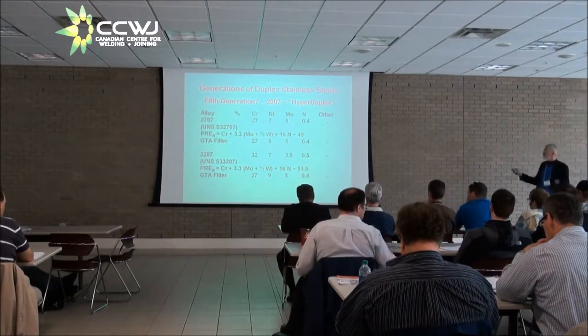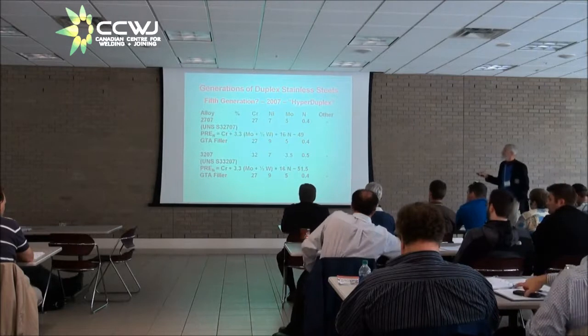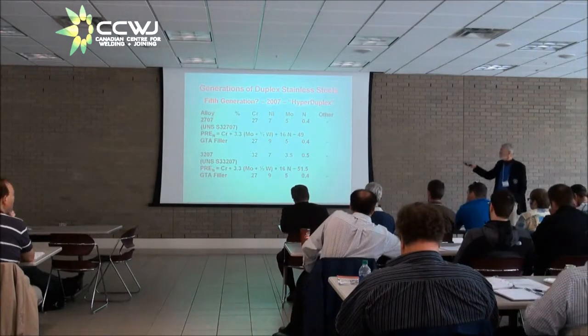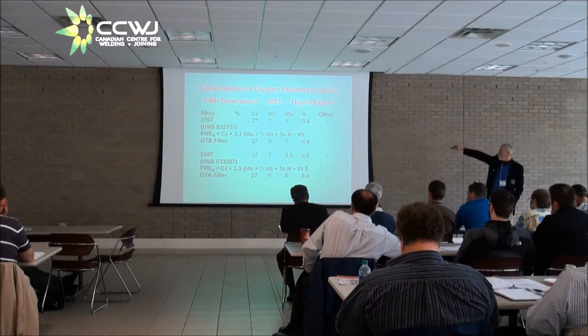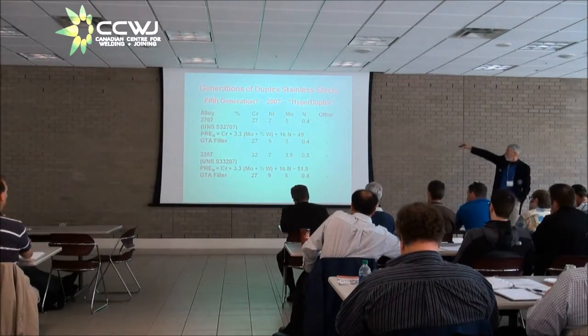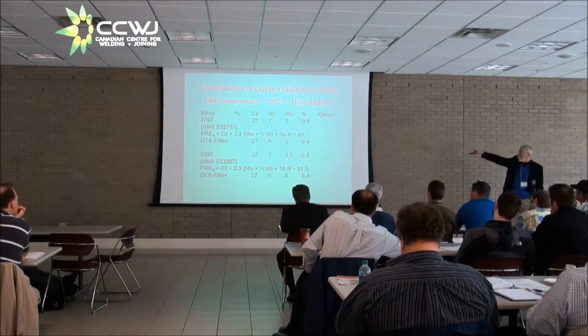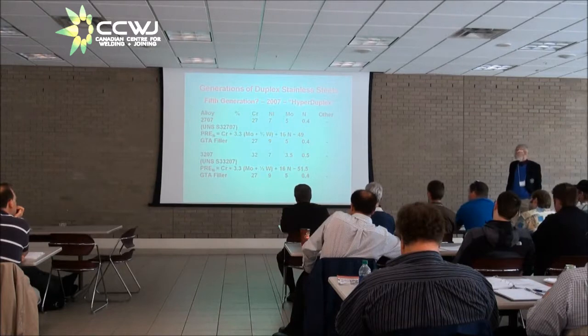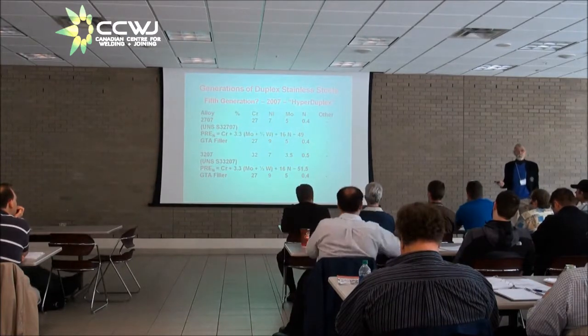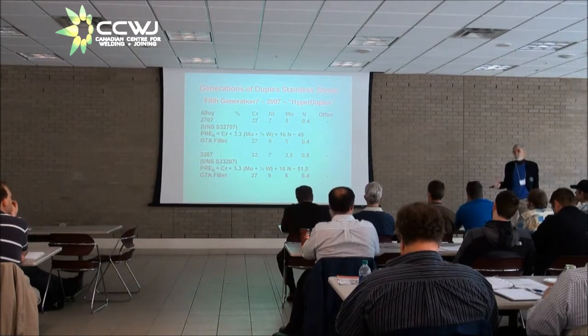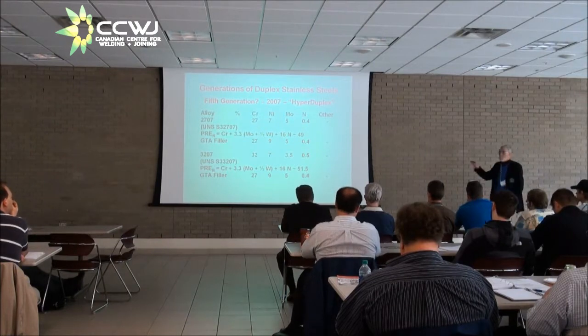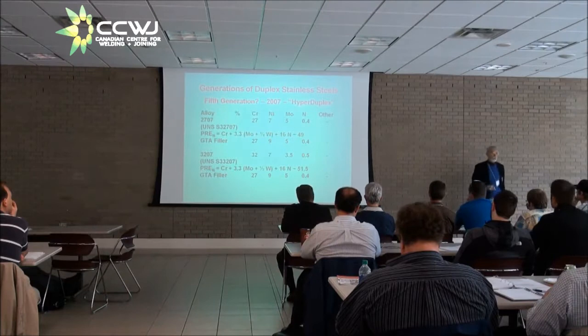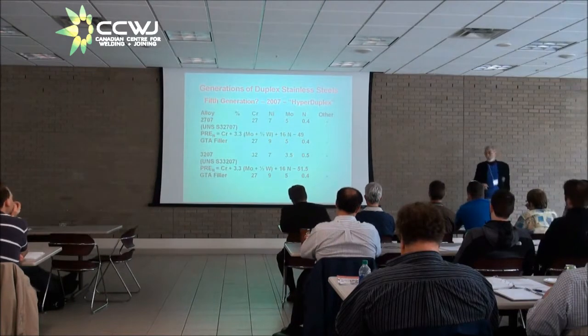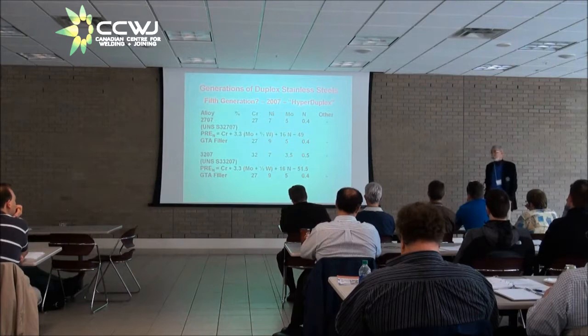The filler material that is proposed for these by Sandvik, who is the purveyor of the material, is 27 chrome, 9 nickel, 5 moly, 0.4 nitrogen, and it's the same filler material for both cases. That filler material is only available as gas tungsten arc filler material. That's the only welding method that's ever been used on those, as far as I know, to any extent. And at the moment, I don't know that there is any commercially significant application of them.